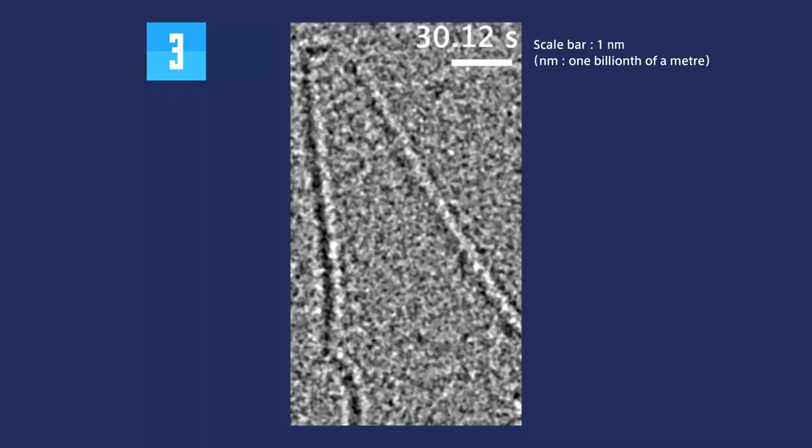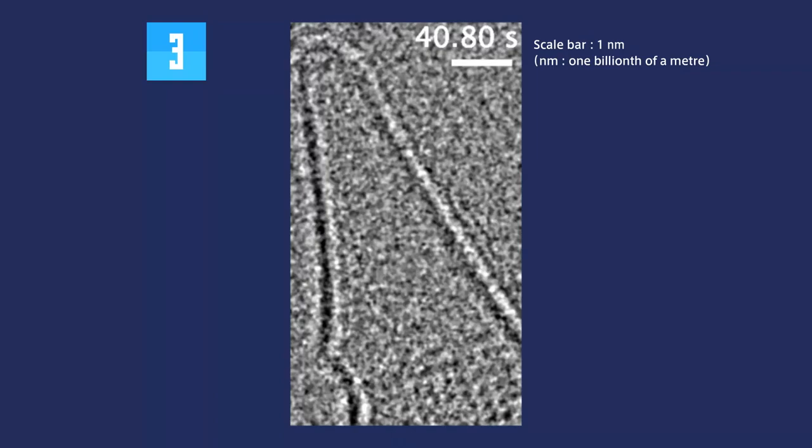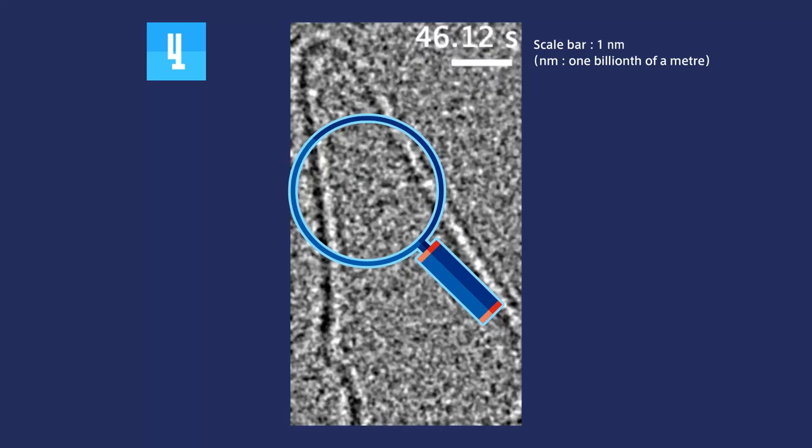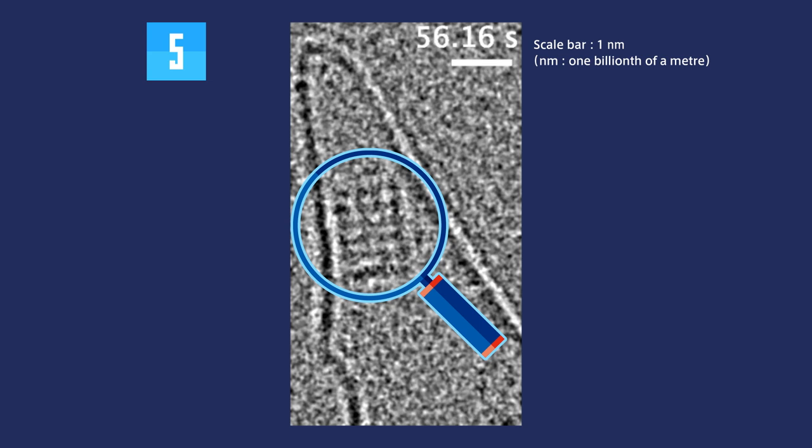We can see here that a four by six rectangular crystal nucleus is formed. The ions fluctuate between a completely unordered state and a partly ordered state. The crystal nucleus appears to be rectangular, but in reality it is actually a cuboid. It consists of 96 ions in total.